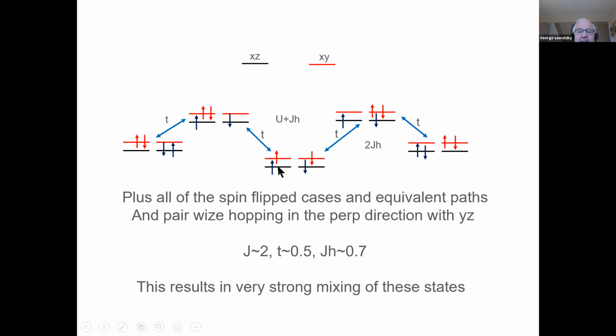So I have the XZ, which is the black one, and the XY, which is the red one. And they both can hop to the neighbor, okay? So I hop one of these spins to a neighboring XZ. No, that was the XY. Okay, this hops to the neighboring XY. By the way, an XY can't hop to an XZ, and an XZ can't hop to an XY. Okay, so the XY hops to the XY on the neighbor, and you get this picture up here, right?